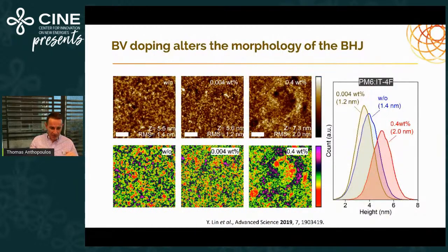And indeed, when we look down on these bulk heterojunction layers without dopant here on the left, all the way to doped systems here on the right, this is the different coloration just to highlight the differences. What we essentially see, and we take these images and convert them to histograms, we see that upon optimal doping concentration, we see a shift of the histogram towards zero height, which means essentially the layer becomes flatter. Or in other words, if it's the same thickness, it will become more dense, grams per unit volume. That essentially justifies the increase in this absorption coefficient that we've been observing across many different bulk heterojunction systems.